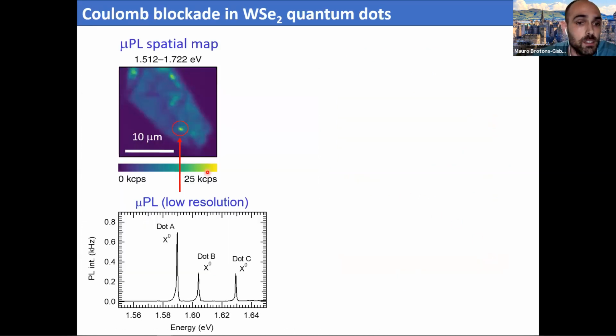So we fabricated the device and we cooled it down to 4 Kelvin. We measured photoluminescence, and this is a spatial map of the photoluminescence in the sample. We have a background emission coming from the exciton of this material. But then here you can see some bright spots. These bright spots correspond to the emission of single photon emitters in the material. So in particular, in this spot here, you can see a photoluminescence spectrum. We have three neutral excitons of three different dots that happen to be in our confocal spot, which is around 500 nanometers in diameter. So what happens when we change the gate voltage in the sample?